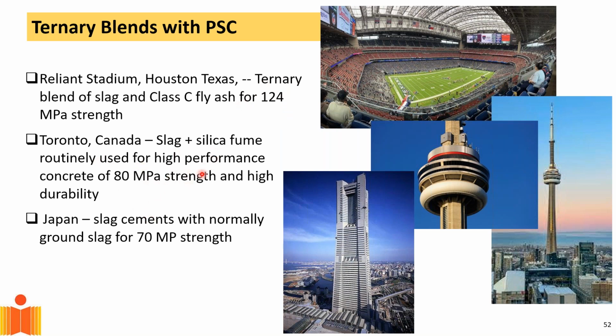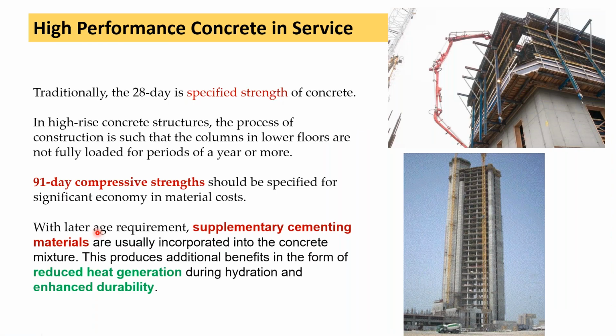In Canada, slag and silica fume. So they're bringing in an additional material, and this has been conventionally used for 80 megapascal concrete. Japan has been using slag cements for about 70 megapascal concrete strengths routinely. So now, if I'm talking about high performance concrete in service, one of the biggest hitches that we have is traditionally we use 28-day strength as our benchmark.